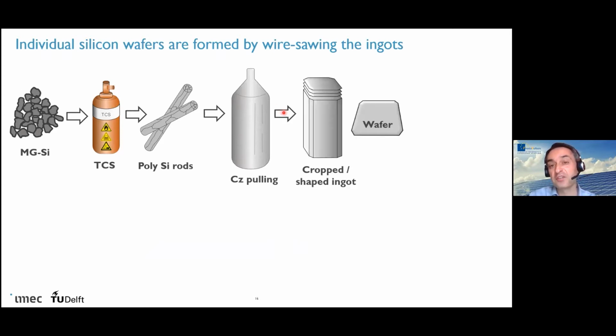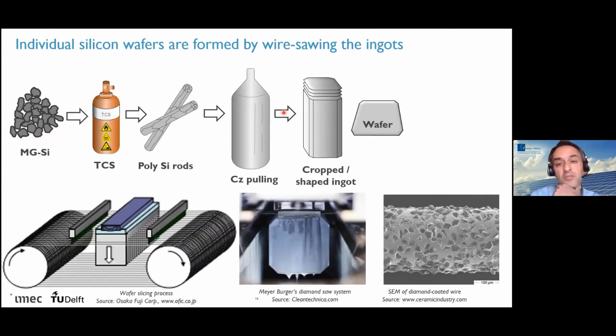And this center part will then be sliced into individual wafers. That is typically done by diamond wire sawing. Basically, we have a very long wire, kilometers long, coated with small nanocrystals of diamond that give an abrasive effect.